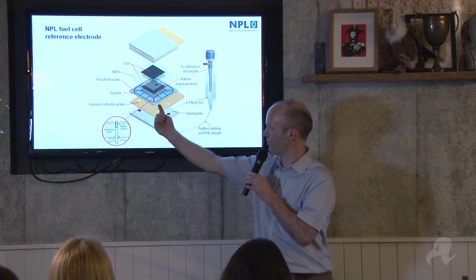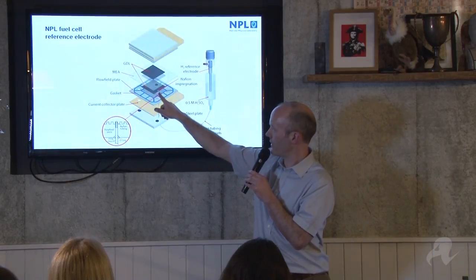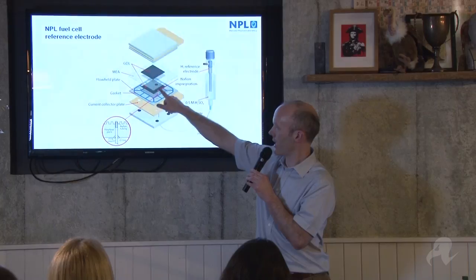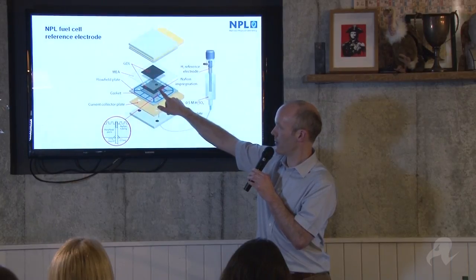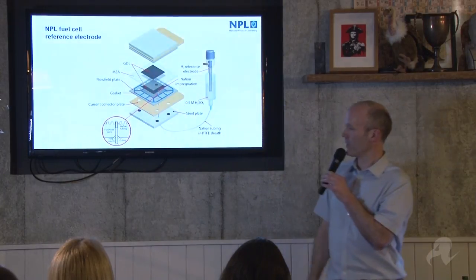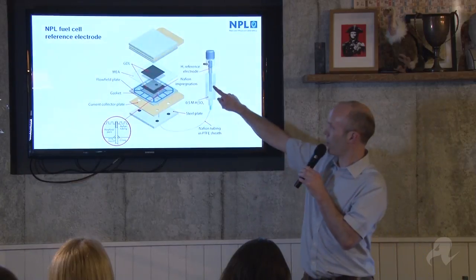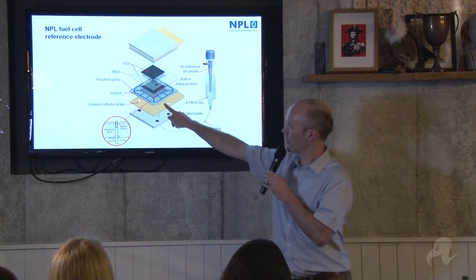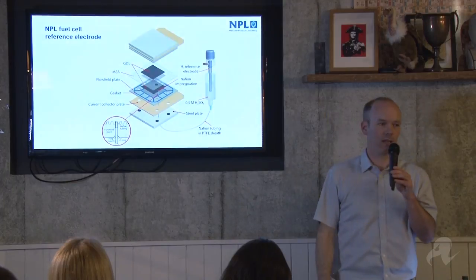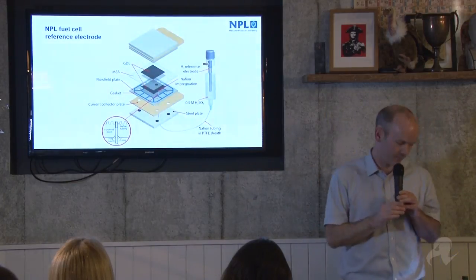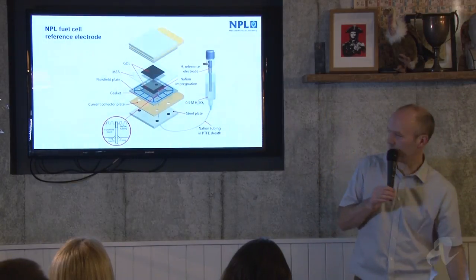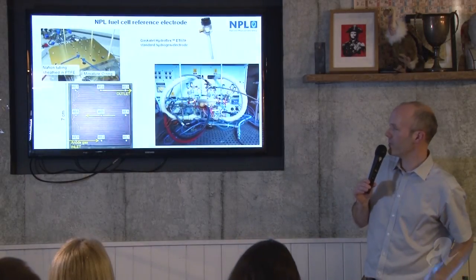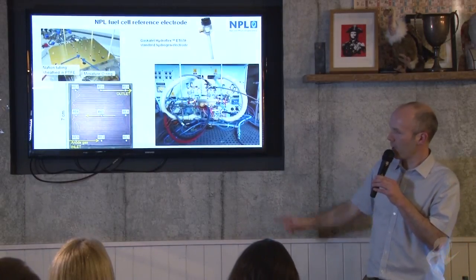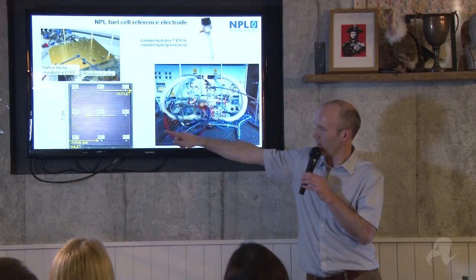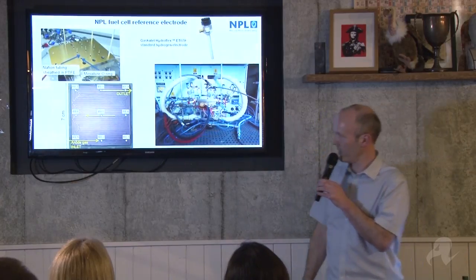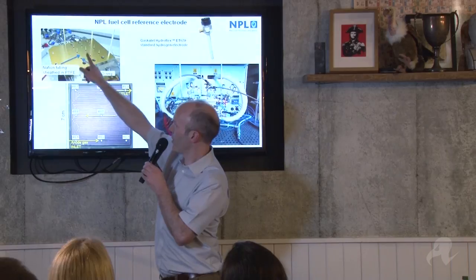We drilled holes all the way through the cell, and then to make the ion conducting path through the gas diffusion layer, we doped it with some Nafion powder. So this way, we had an ion conducting path all the way from our reference electrode to the surface of the fuel cell electrode, whether it be anode or cathode. And this allows us to make an array of these. So we made a 3x3 array across the active area of the cell, and you can see the 9 reference electrodes poking out here.